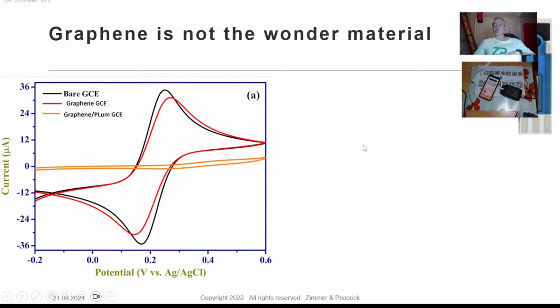Graphene, people think that it's some sort of real wonder material and it's going to really help with biosensor sensitivity. This data is not my data, this is that author's data, but it shows you that graphene is not the wonder material that people say it is, because actually your voltammetry is better with graphite than it is with graphene. So I think the graphene bubble will sort of pass. Once upon a time it was multi-wall carbon nanotubes, then it became single-wall carbon nanotubes as the wonder material. Now at the moment it's graphene, but these things will come and go. When you put the polyluminol on, you actually lose signal altogether. Now the source of the signal here is a mixture of probably ferroferic.